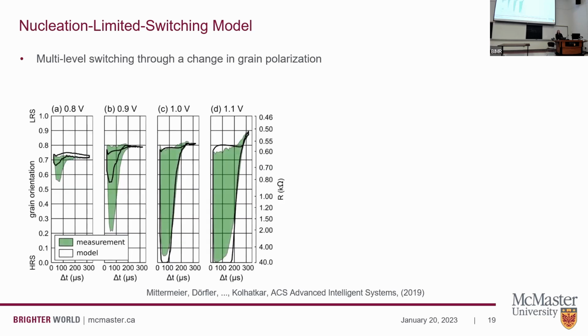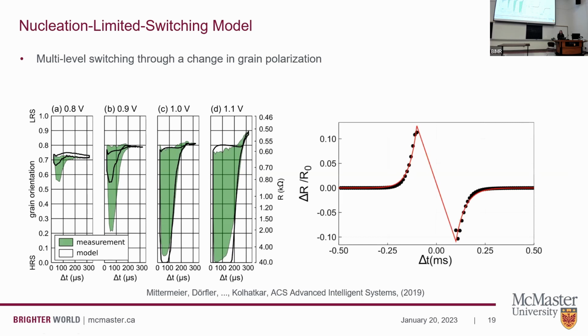So here are the results of the simulations that we got. What we see here is on the y-axis, we have the grain orientation, so whether the grains are closer to the low resistance state or the high resistance state. And we look at this as a function of the time, the two action potentials. The black empty curve corresponds to the simulation model, and the green curve corresponds to the measurements. So using this curve, we started by getting a simulated STDP curve and comparing it to our experimental results. That's what we see on this graph here, where the black dots correspond to the experimental results, and the red curve corresponds to the theoretical curve. So we can see that we have